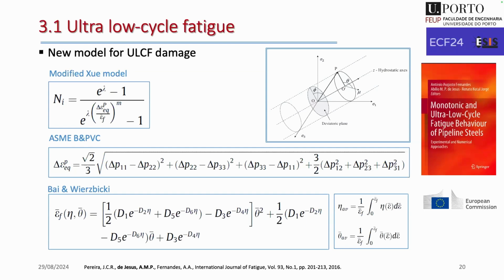And the ductile fracture was also modeled. It was already 10 years ago, time passed too fast, but at the time, for the fracture strain, we used the Bai-Wierzbicki approach, which defines the fracture strain as a function of the triaxiality and the load angle parameters of the material. So fracture strain is not a constant of the material.